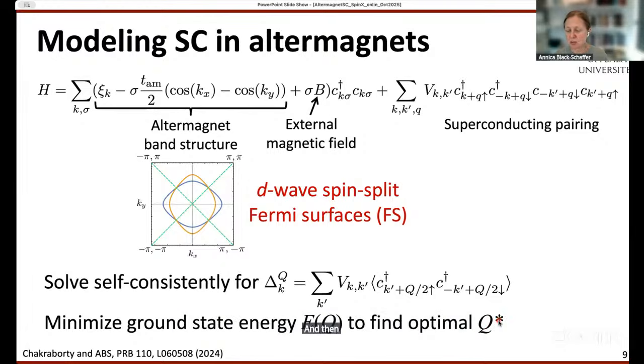With mean field theory, I create a mean field that is my Cooper pairs, and I'm going to do this allowing for a finite Q. So I calculate this delta as a function of Q, for every single Q or on a grid. For each, I find the solution, and then I minimize the ground state energy as a function of Q, and I find some optimal Q star, and that is going to be the true ground state of the system. Sometimes Q star is 0, and then I'm just in the BCS limit. And if Q star is finite, I have this FFLO pairing.